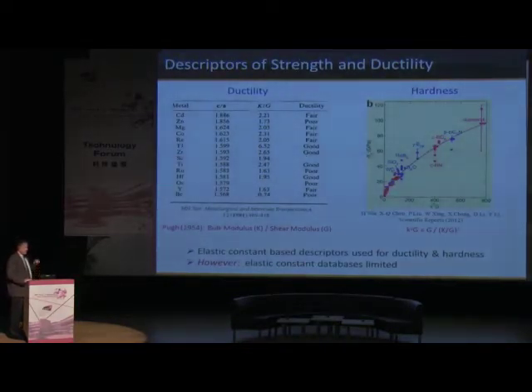Okay, so the whole key with this computational screening for materials is to have what we call descriptors. That is a certain property that we can calculate in a high throughput mode that correlates with a more complicated property that we're interested in for an engineering application. A complex property is this ductility or hardness of a material. That's a very hard thing to calculate directly on the computer. But what people have found through years of research is that there are certain discriminators or predictors based solely on the elastic constants of the material. So instead of that fourth rank tensor, what I'm showing here is simply bulk modulus and shear modulus.